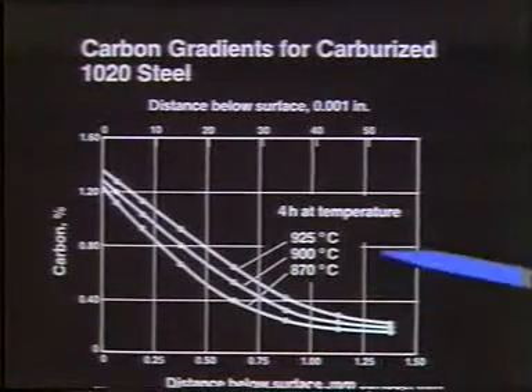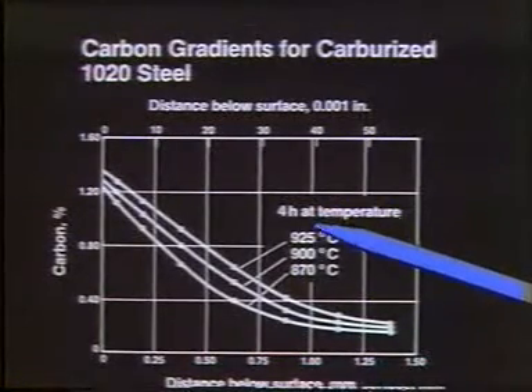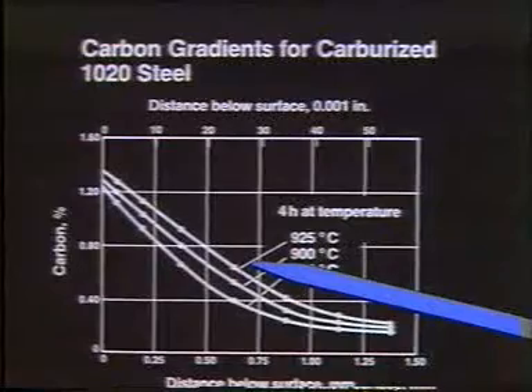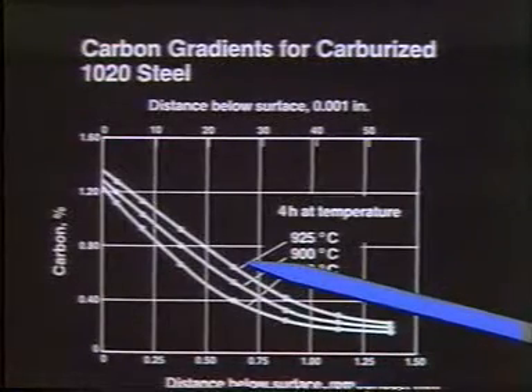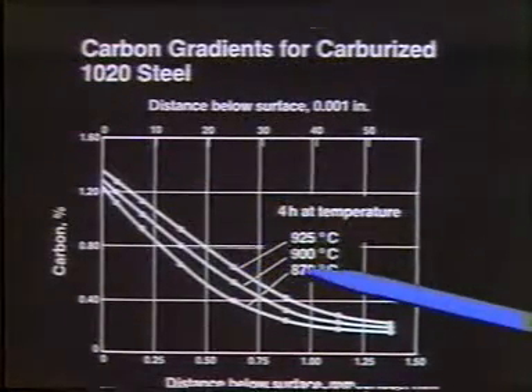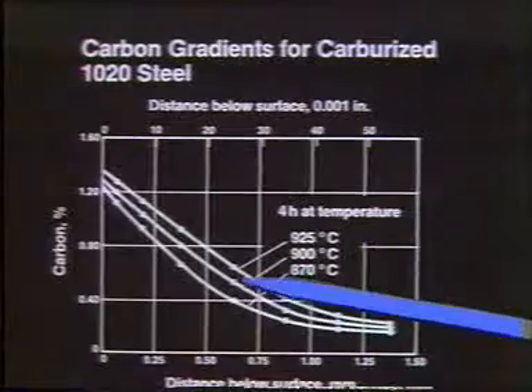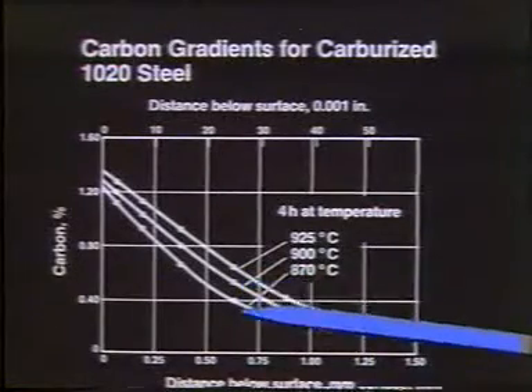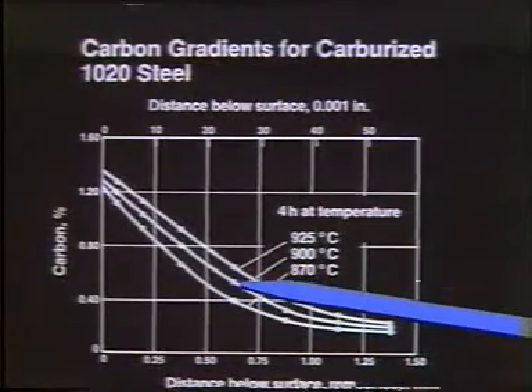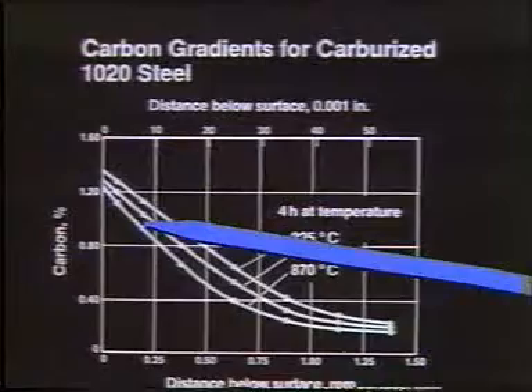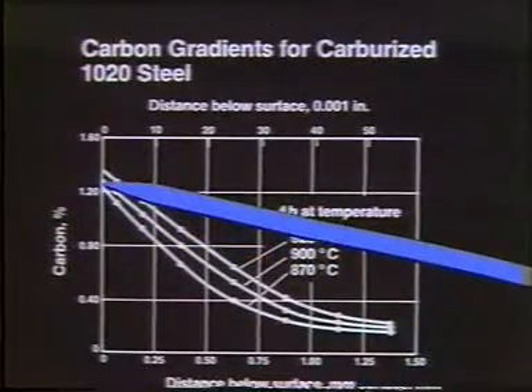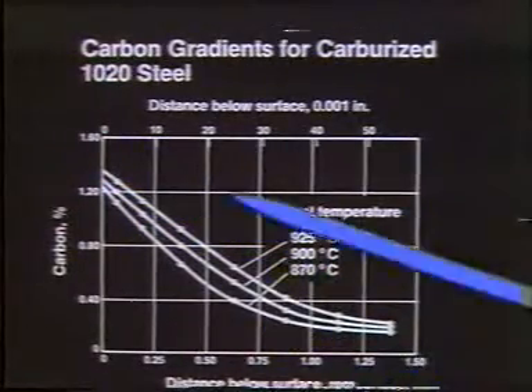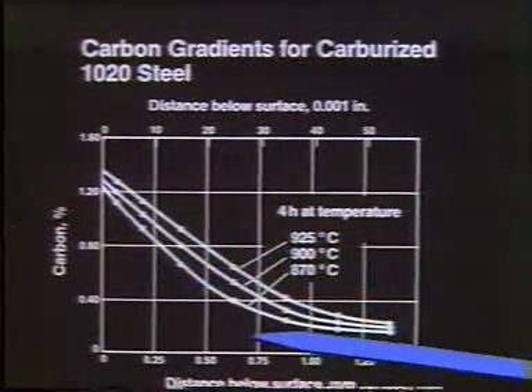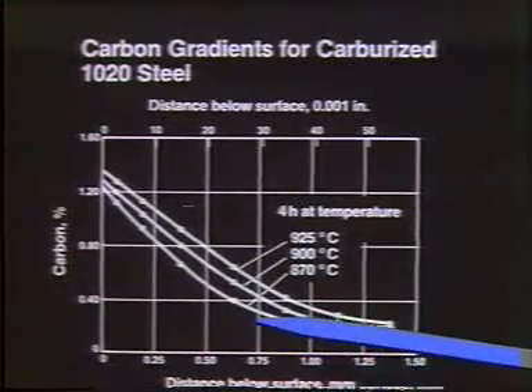Right? If we looked at this at a high temperature, we find that the carbon level that we would have at any position underneath the surface is going to be higher than if we carburized it at a lower temperature or a still lower temperature. So it's going to be dependent not only on the time, but the temperature at time, and it's also going to be dependent upon the alloy that we have.